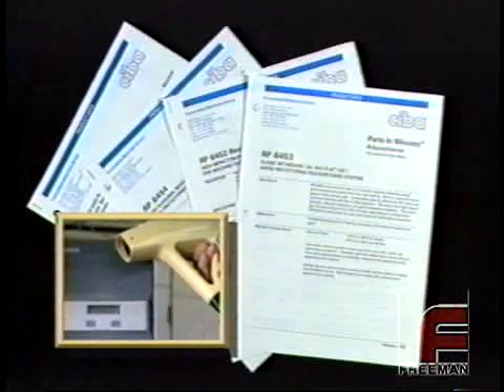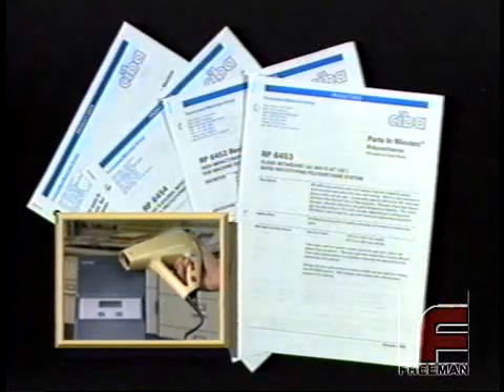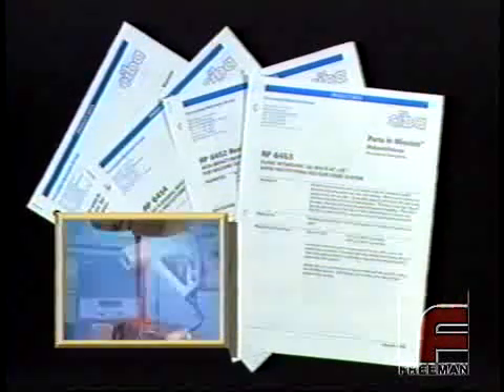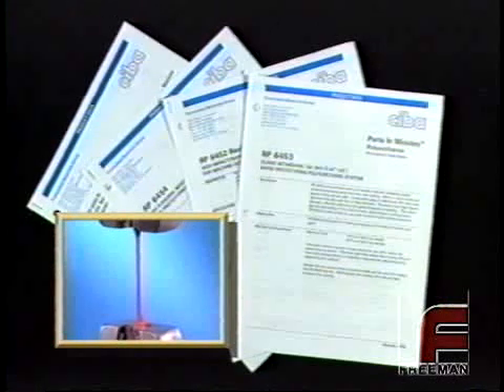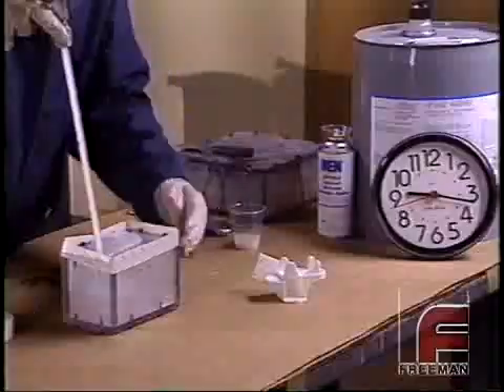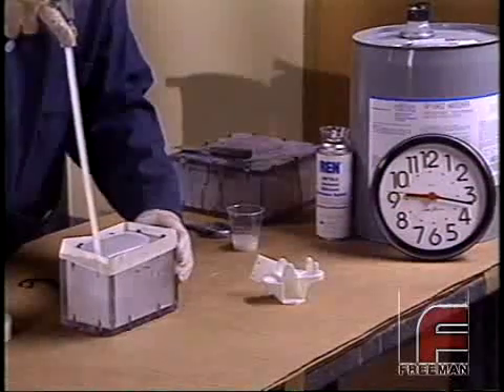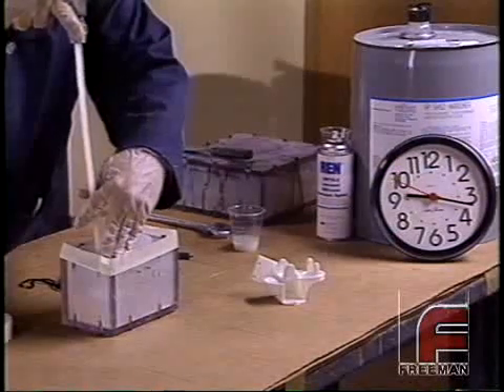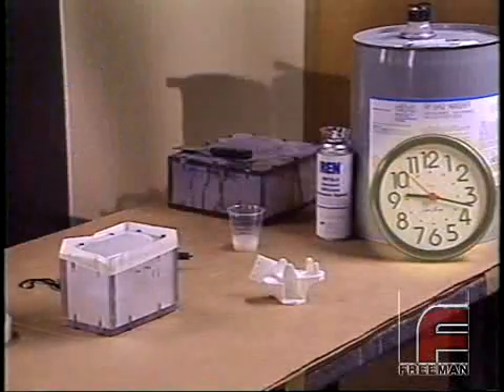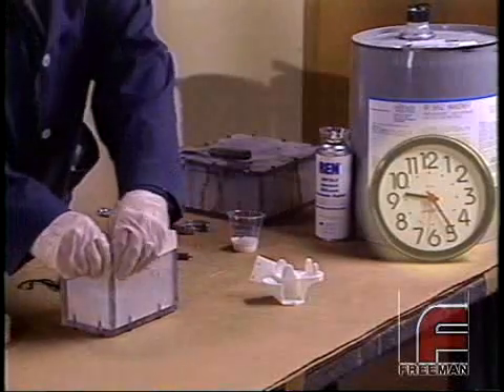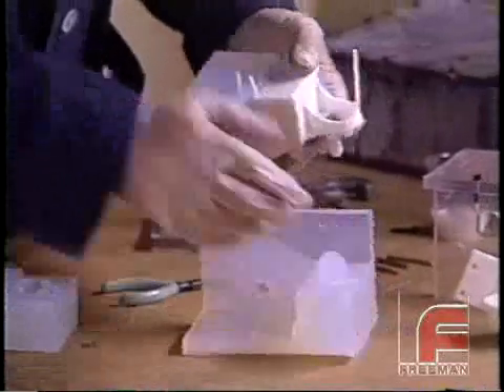Before starting work with the Parts in Minutes polyurethanes, Prototype Techniques conducted a series of tests to verify the product performance characteristics included on Ciba's data sheets. They were a little concerned about the accuracy of the spec sheets, so we did actual independent impact and heat deflection temperature testing with an independent lab before we even started to shoot parts, because of our bad experiences in the past with what people advertise on their spec sheets. And the Ciba spec sheets actually understated the impact strength of the material by a fairly substantial amount. It's always better to find out that the stuff is better than you thought it was going to be, rather than to find out that it's not even as good as it was supposed to be.